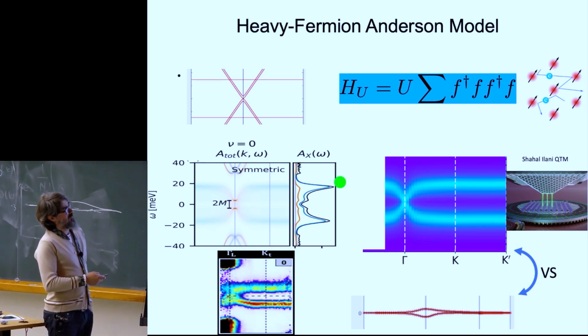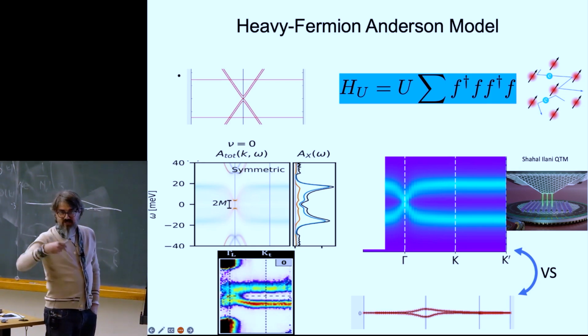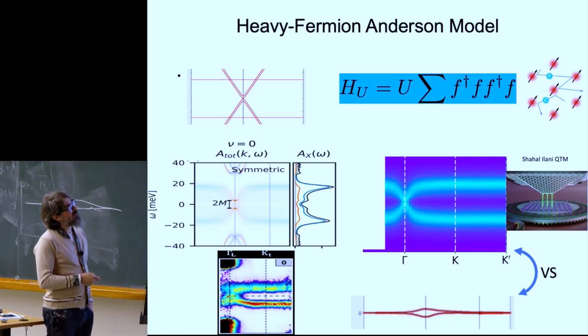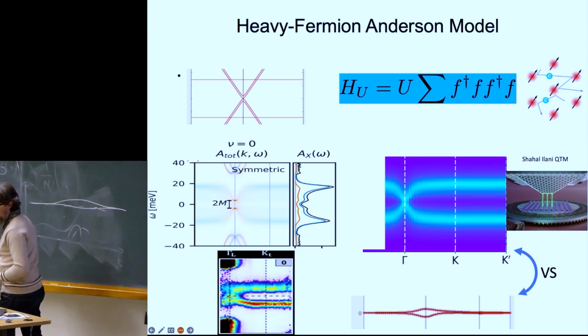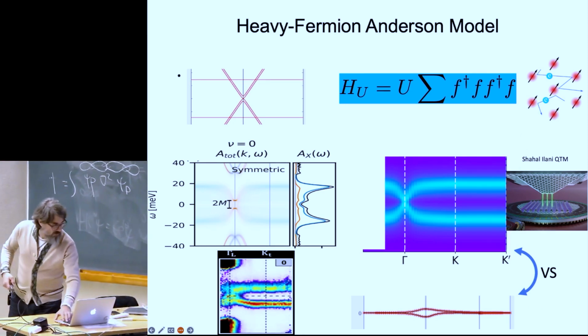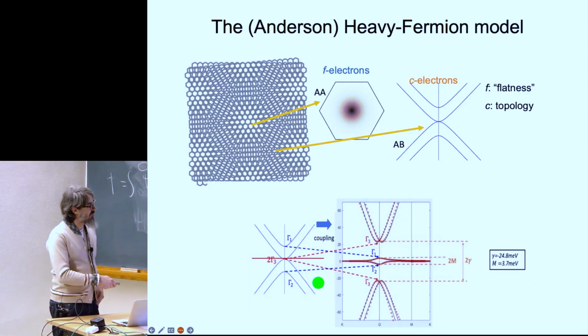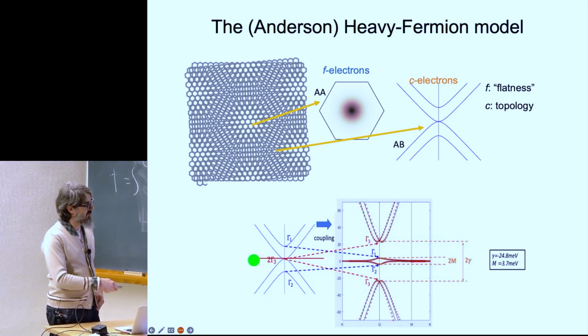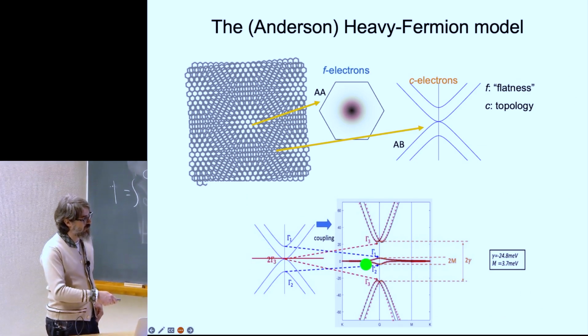So indeed, you take the Coulomb interaction, which is some screened interaction because you have a metallic gate, and the screened interaction, when you project it into this F electron and C electron basis, that gives you these flat bands. So as I said here, most of the band is F electron. You can see it here. Most of the band is F electron, but around the gamma point, it's the C electron.